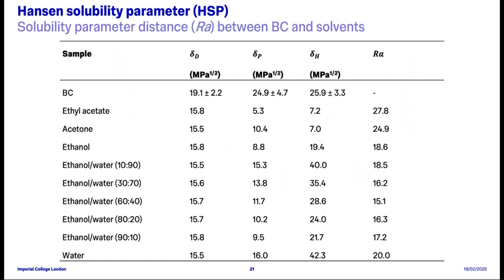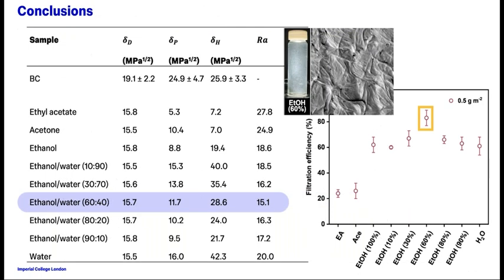Taking these numbers further to calculate the solubility parameter distance, it can be seen that the value of the solubility parameter distance is the lowest for the 60% ethanol-water mixture. This indicates the solubility similarity between bacterial cellulose and these specific solvents and confirms our earlier observation in filtration properties by experiments. So in short, today we have demonstrated that there's a very strong agreement between the solubility parameter distance and the filtration properties obtained experimentally, and suggest that the use of solubility parameters in understanding bacterial cellulose dispersion and material processing will be helpful.